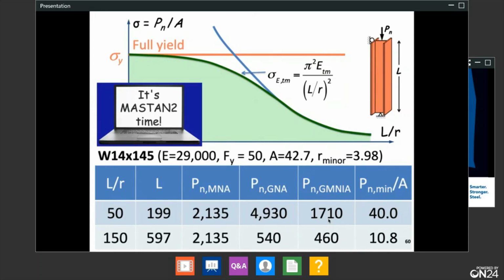When I divide by the area, the GMNIA results, MASTAN has cooked into it. It has calculated the strength of our column. And at an L/r ratio of 50, our column has a strength of 40 ksi. At an L/r ratio of 150, it has a strength of just about 11 ksi, 10.8. So we haven't used any column curve out of AISC or anything. It's just that programs like MASTAN that have the ability to do a full geometric and material nonlinear analysis that accounts for partial yielding and initial imperfections, they can predict the strength of the column for you.